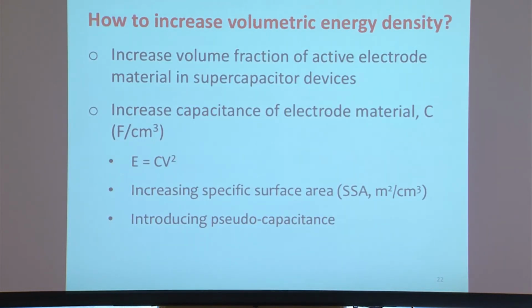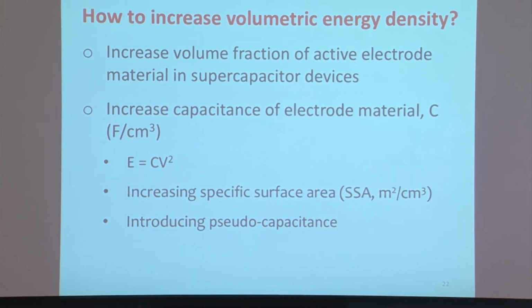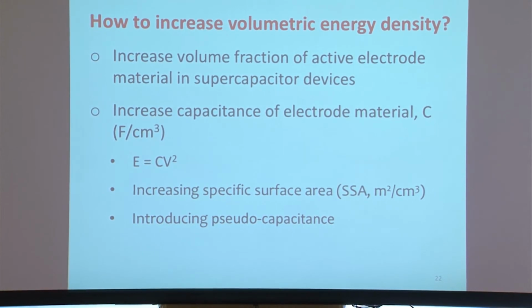So how can we increase the energy density of a supercapacitor? There are several ways you can do that. One way is to increase the volume fraction of active materials in the device. I will explain that later. Another is to increase the capacitance of electrode materials, capital C in this case. The E here is energy. If you look at that equation, the energy stored is proportional to C. If you increase C, then you increase energy. The C, again, is proportional to the useful specific surface area. The C can also be increased by introducing pseudocapacitance through chemical redox reactions.